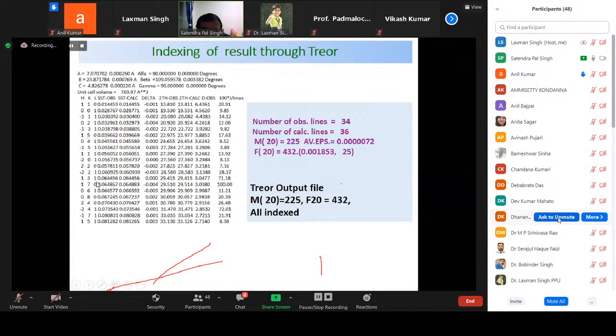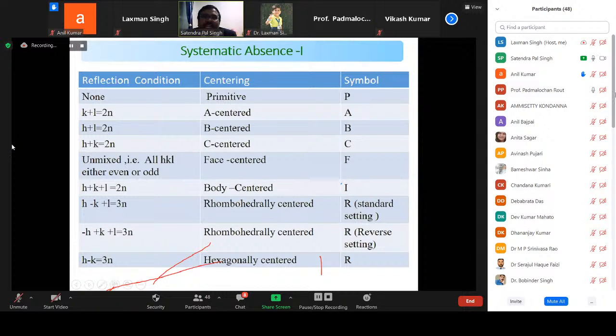So this is the HKL, this is the 2 theta observed value and the calculated values, and then we have the d spacings. Everything is present here. Then by knowing the HKLs present here, we are going to decide the lattice type. What is the lattice type: A type, B type, C type, or primitive type? So the next step is to find the systematic absences. How to do that? If you see the list of all the indexed planes, you have to see whether any specific conditions occur.